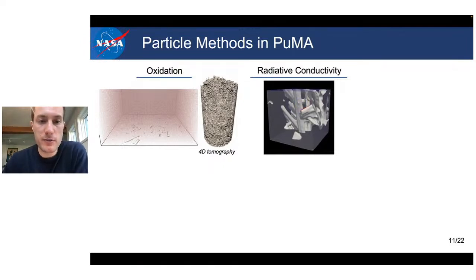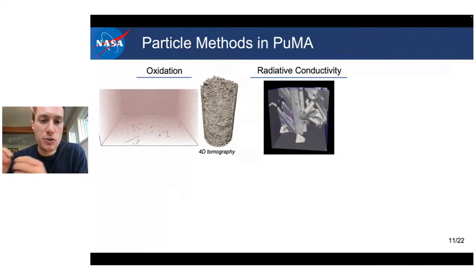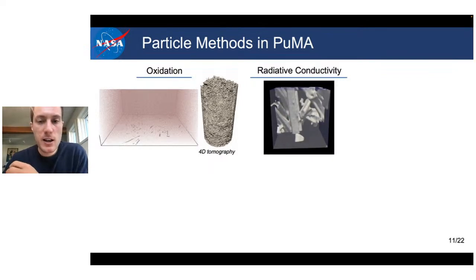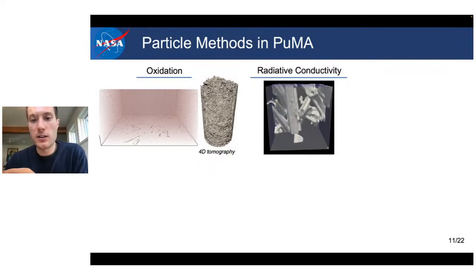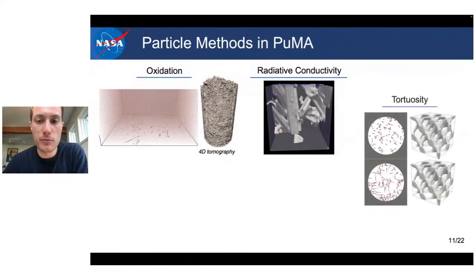The radiative conductivity is very important for high temperatures. And we do this by scattering a whole bunch of particles from different spots, and then tracking how far these particles are traveling until they hit the solid surface. And then you can do statistics on how far a particle is likely to travel. And from that estimate, you can compute what is called the extinction coefficient, which is necessary to compute the radiative conductivity.